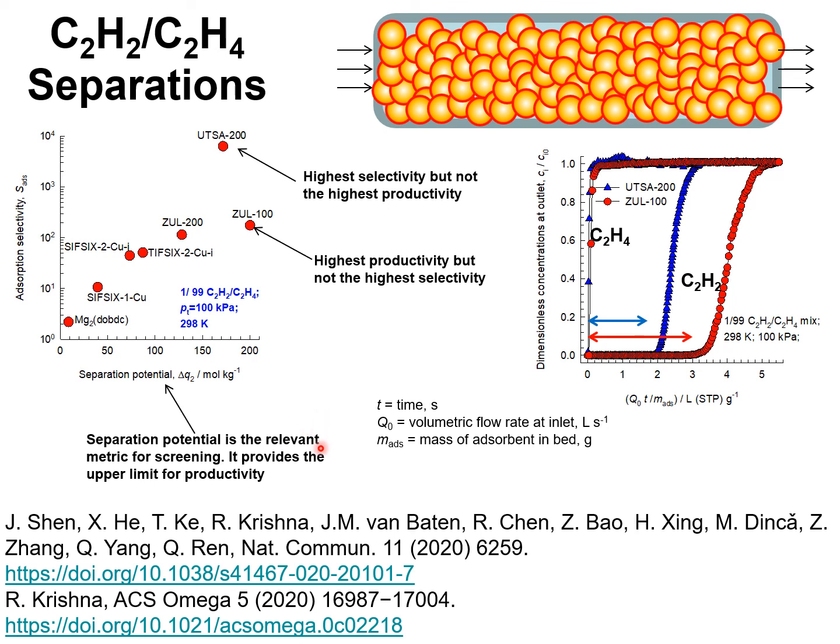In the transient breakthrough simulations, we take proper account of the intracrystalline diffusion as well as the fact that the concentration fronts in the actual adsorber will not traverse the column in the form of shock waves, but will have a more distended character that reflects the finite selectivity of adsorption with a given MOF.